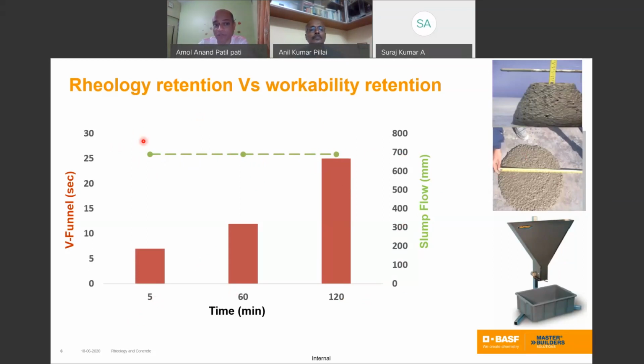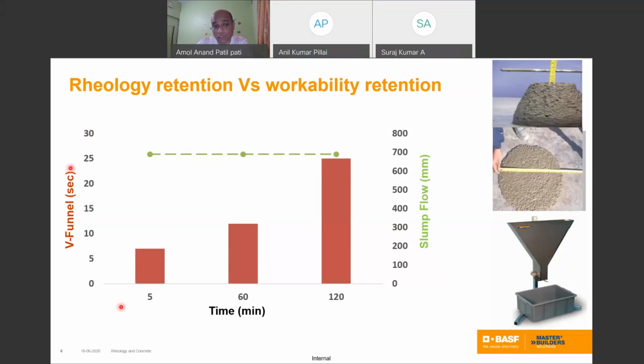Now see the same concrete. If I measure the V funnel value, here is my photo. I hope you understand the V funnel instrument. If I measure the V funnel value at 5 minutes, it is 7 seconds. This y-axis is in seconds. So the 5 minute concrete gives a viscosity in terms of V funnel of 7 seconds. The same concrete tested at 60 minutes has viscosity increasing from 7 seconds up to 12 seconds. Tested from 60 minutes to 120 minutes, the viscosity increases to 25 seconds.